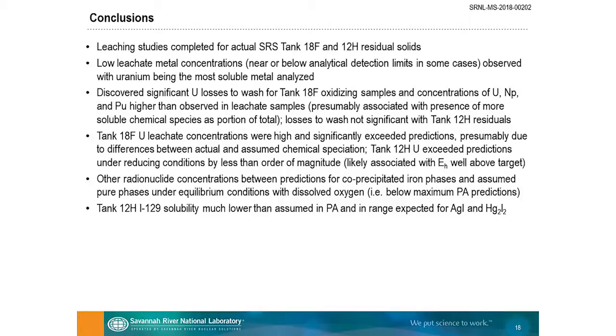It turns out uranium is not one of the biggest dose drivers, but they're evaluating all this now with regard to how it impacts their performance assessments. But the other radionuclide concentrations were between predictions for coprecipitated phases and assumed pure phases. In other words, they were below the maximum PA predictions. So in general, the results were good and should have a positive impact on the performance assessments.